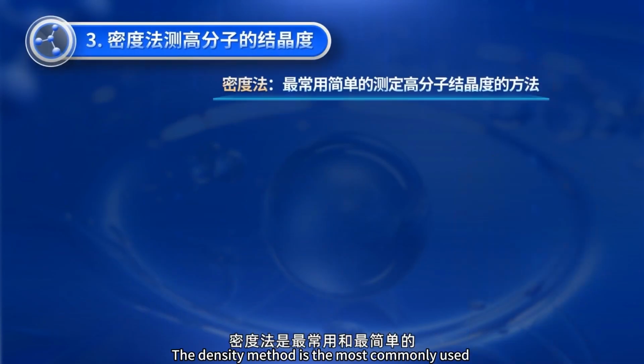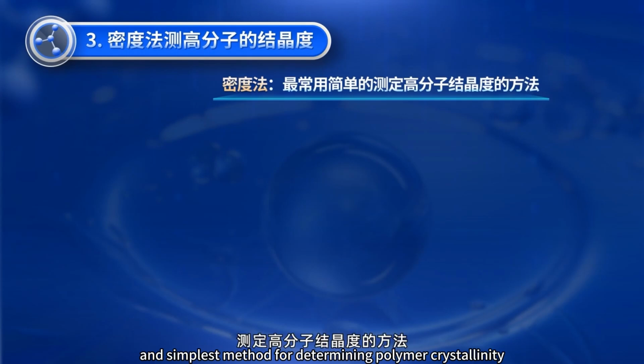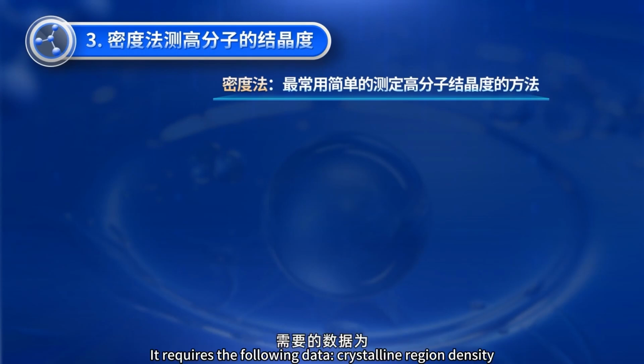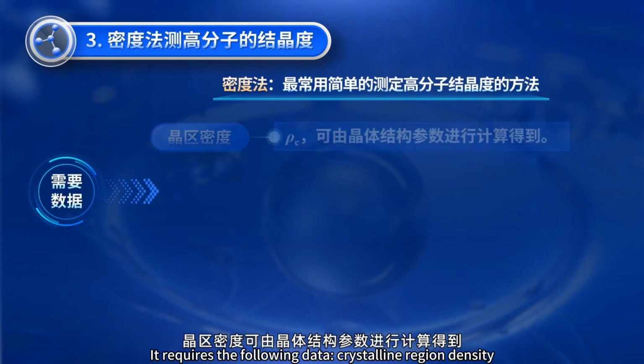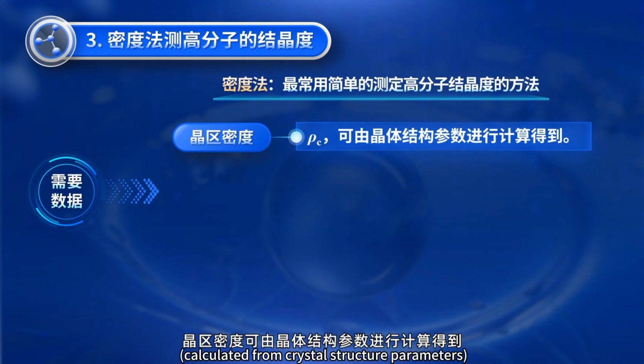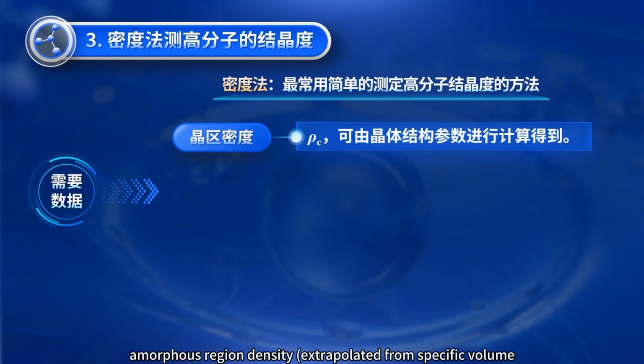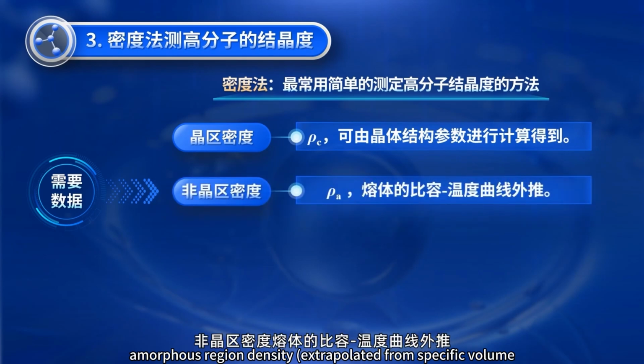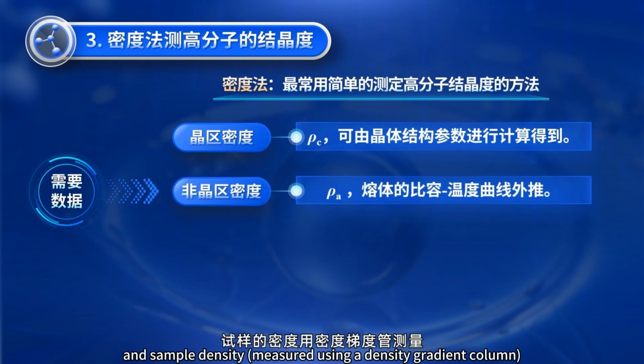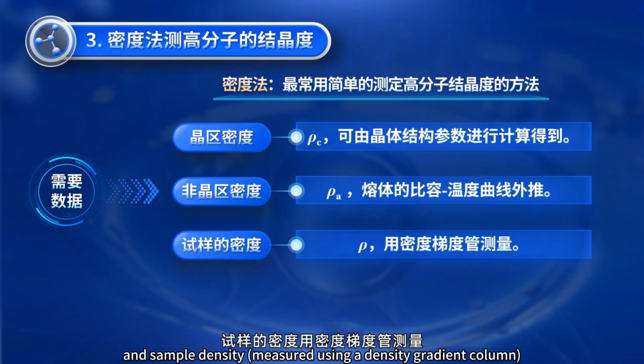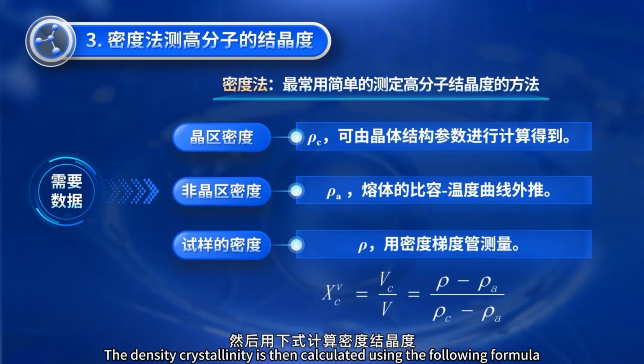The density method is the most commonly used and simplest method for determining polymer crystallinity. It requires the following data: crystalline region density calculated from the crystal's structure parameters, amorphous region density extrapolated from specific volume temperature curves of the melt, and sample density measured using a density gradient column. The density crystallinity is then calculated using the following formula.